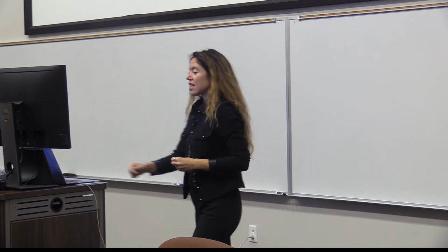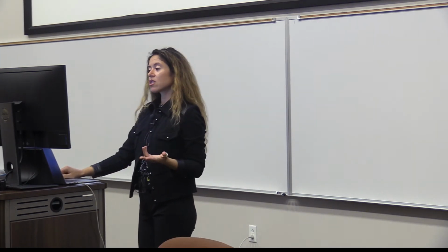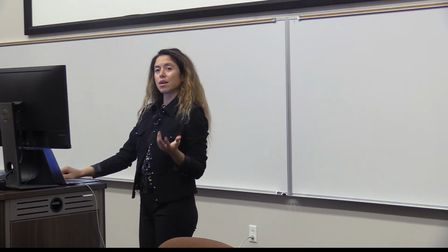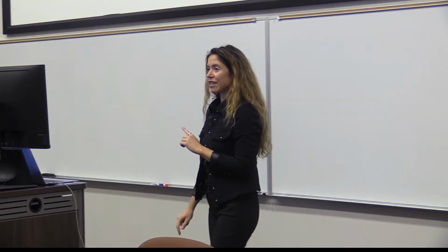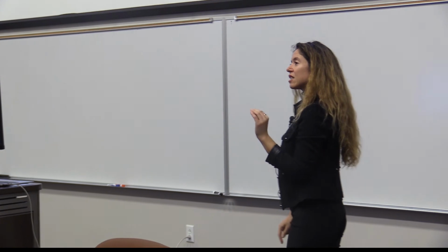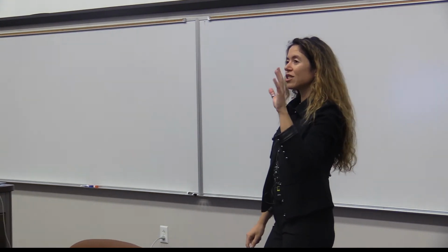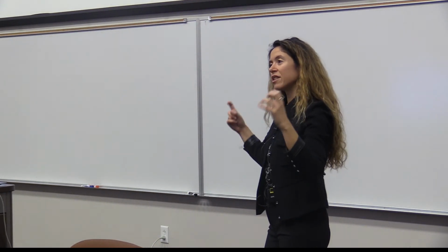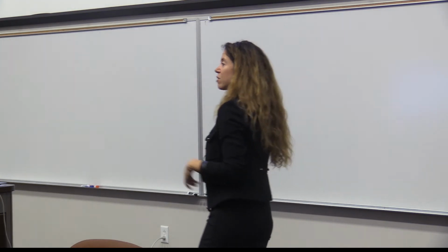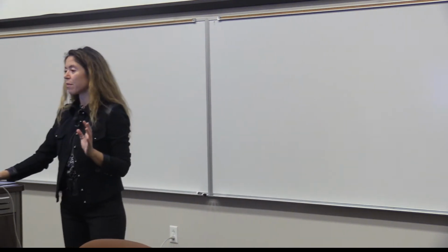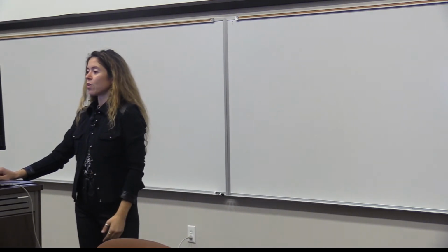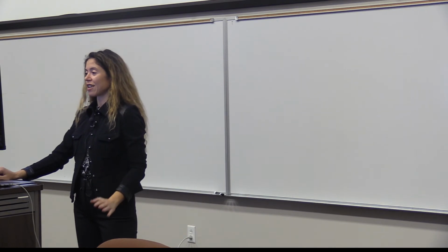Okay? So this is expected for entangled polymers, but the exponents that we see here for this behavior are representative of that gray zone where you don't yet have what is called in the theory entangled systems. So it is really a system that one cannot say is very entangled.